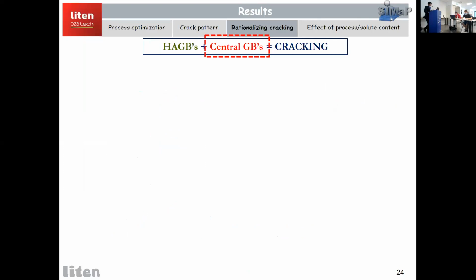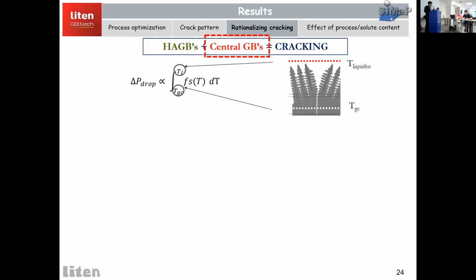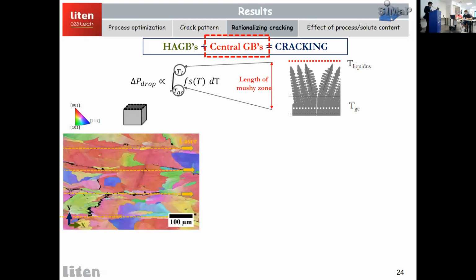Now to identify why the central grain boundaries are cracking, as we have seen in the equation of pressure drop, the integrals go from coalescence temperature to the liquidus. So if we look at the bounds of these two temperatures, and within these bounds, what is the length of mushy zone? If we are able to quantify this on a microstructure level, we can have an idea about why cracking can be along the center lines.